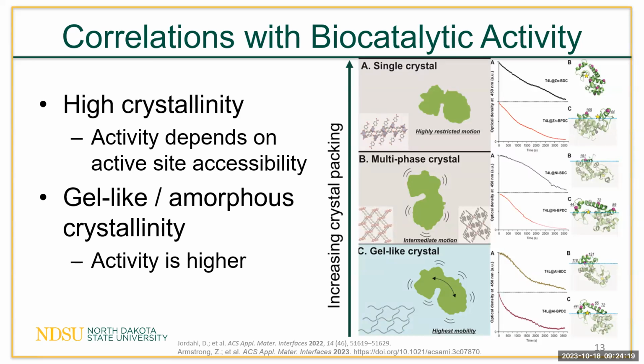What this means to us is that since these gel-like crystals that are very amorphous, where we don't see high crystallinity with XRD, have high activity, they're likely to be flexible and allow proteins to move and bend and be able to utilize that active site for this large substrate, since these activity tests are done on cell walls, which is what lysozyme breaks down.